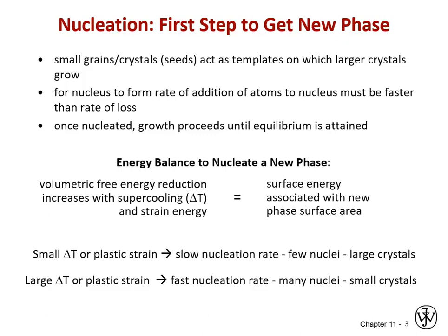So if you're thinking in terms of the properties that we would need from a microstructure, just from this, if all we were going to do was nucleate one new phase and then go put the material into service, most of our mechanical properties, we remember, are favored by a refined grain structure, lots of small crystals. So already we can think, if I gave a phase transformation process a tremendous drive to occur, I would probably get a nice grain refined structure. I'd get a nice small grain sized microstructure, which would give me a high strength.